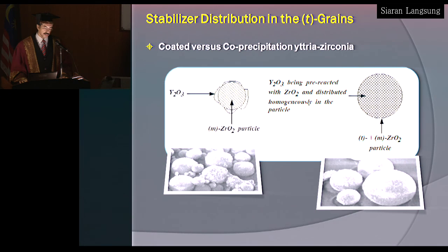Now, there is a dispute about stabilizer distribution, how the yttria is distributed throughout the material, the starting material in powder form. There are 2 arguments. One is coating yttria on the surface of the particle, and the other is to co-precipitate the stabilizer into the structure. What that diagram shows are the 2 effects. In the first one, yttria is added onto the surface. The second one is basically infused with the monoclinic particle.